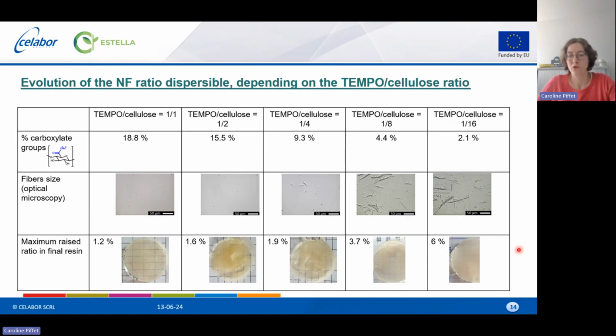So this is, of course, the ratio for one kind of resin. It will depend on the viscosity and the ratio of the precursors and the hardeners. But this shows that by tuning the functionalization ratio, we can tune also the ratio of additive that can be included in those resins. For the next steps of the project, we selected two types of functionalization because we cannot work on everything. And so we choose to work on this one, the thinner and shorter fiber, and on the 1/8 to have sufficiently carboxylated content.